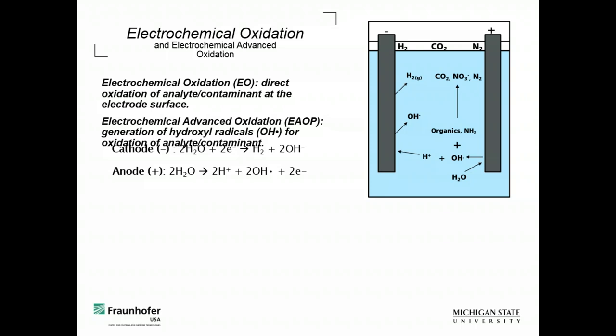You can do mineralization. However, if you look here at the cathode reaction, it's kind of hard to see, but we are making hydrogen gas. So we generate about 0.4 liters of hydrogen per amp hour. So this is one thing to consider, that we do generate significant hydrogen gas, especially when we're using diamond cathodes. This reaction occurs very, very readily on diamond.